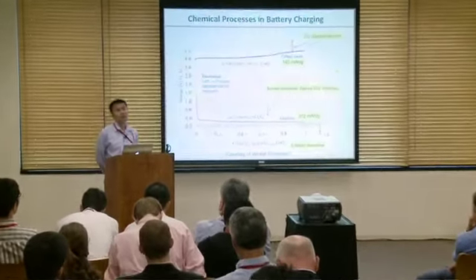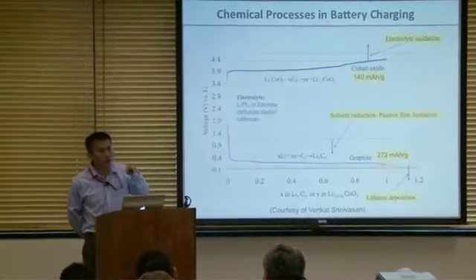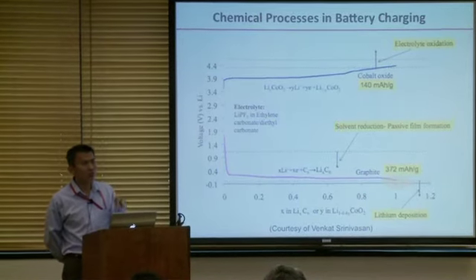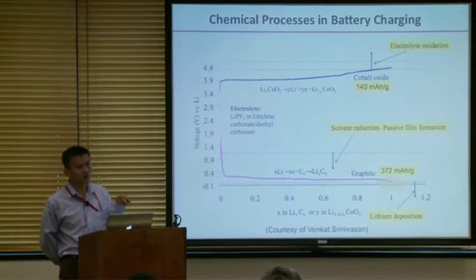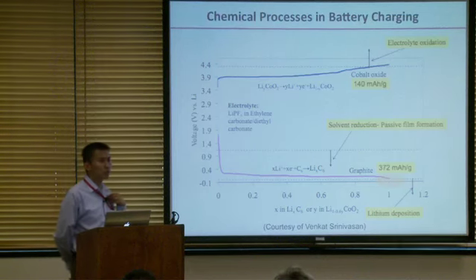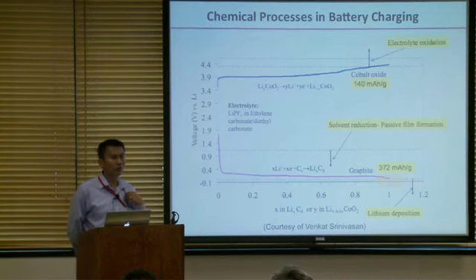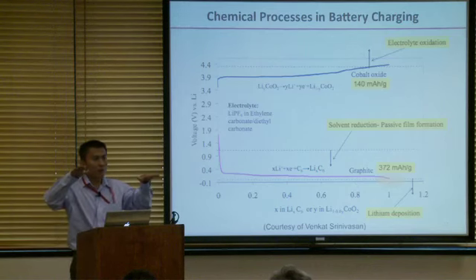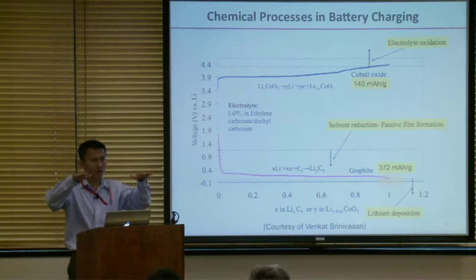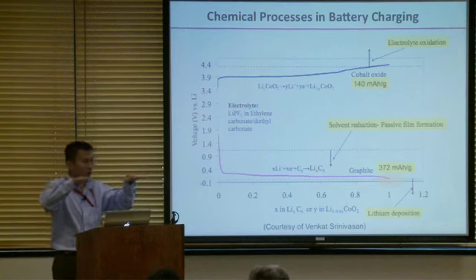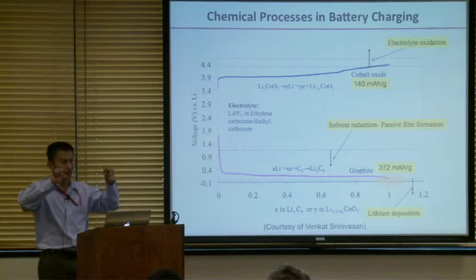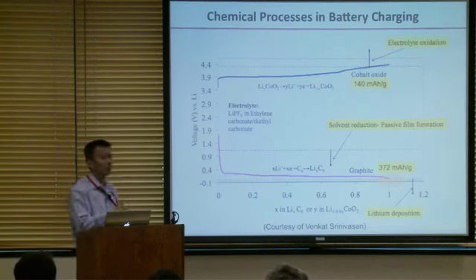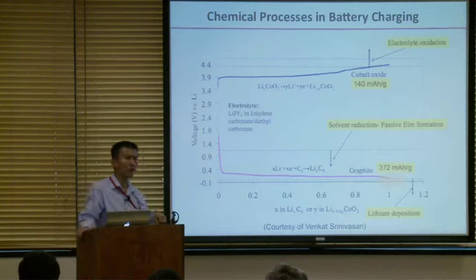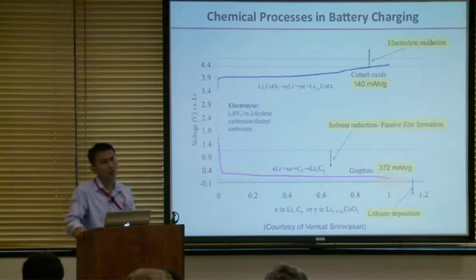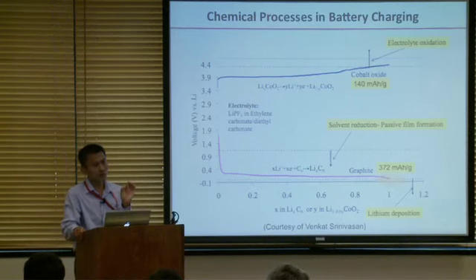And people don't do that because this requires 3 electrodes inside the batteries. And the engineering design is so much more challenging. The cost is so much higher. People don't do that. At the end, how do you control the voltage? You need to balance how much material you put into the positive and negative electrode. You calculate that exactly, and you do the testing. With a certain materials balance, certain ratios, you always control the voltage within a certain range. Don't go over to the dangerous potential. A lot of experience is built inside those controls.